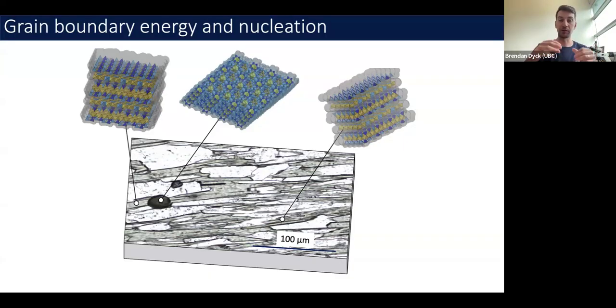And different chlorite grains will have different orientations. And we can look at those orientations and we could look at what, for example, the basal cleavage of those orientations, what the surface interaction, in the kind of gray circles here, we're looking at the topography of the van der Waals forces or interactions on that surface. And then we could look at the same thing, for example, with tourmaline. And there's going to be some configurations where this tourmaline is going to be in a lower energy orientation relationship with the chlorite than other configurations of that tourmaline might be. And now when we think about this from a nucleation perspective, that will lower the free energy, or lower the grain boundary energy at that contact of that new nuclei forming, which will actually make it easier for that nucleation event to be successful or to occur.